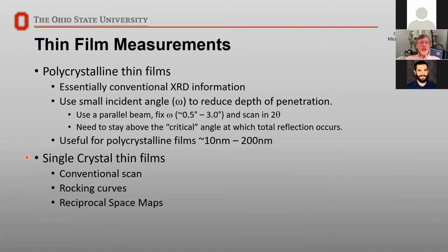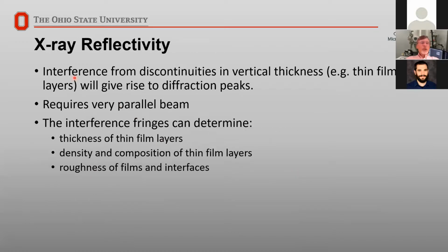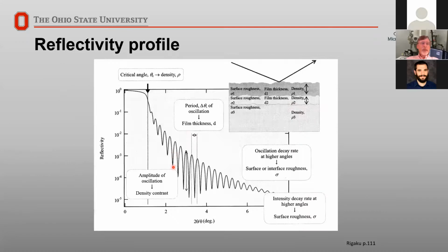But we can also start to look at single crystal thin films. This would be very important for the semiconductor industry or growth type of things. And we can do conventional scanning to see the distribution. And we can do rocking curves and reciprocal space maps to look for defects in the material. But there's another measurement called X-ray reflectivity, which allows us to see the thicknesses of the layers that we've grown. So any discontinuity acts almost like a plane or a difference in scattering. So you need a very parallel beam, and you come in at a very shallow angle. And then our interference fringes will tell us the thickness of the layer, density, and we can estimate composition and roughness of the layers. So what you get, and now look at these angles here.